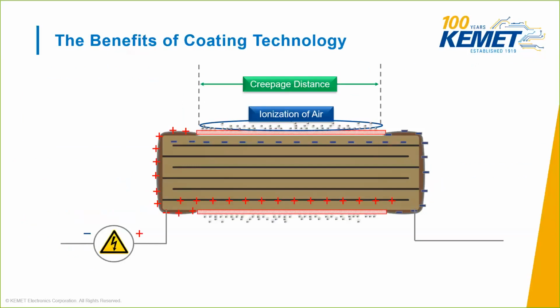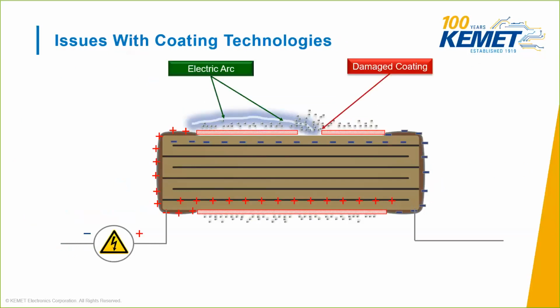Improving this stability reduces the ionization of the air, increases the inception voltage along the surface, thereby reducing the potential for arcing and improving the voltage performance of the capacitor. Not only does this add a cost to the process, care must be taken not to damage the thin coating on the MLCC, which exposes the dielectric to air, creating an opportunity for ionization and arcing.